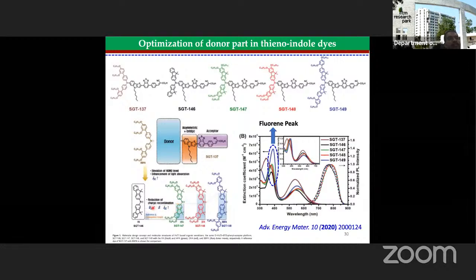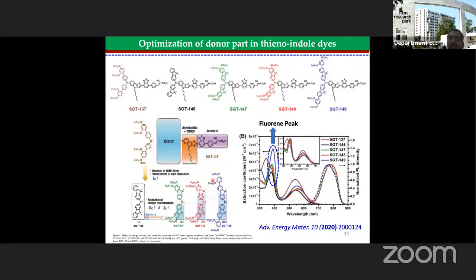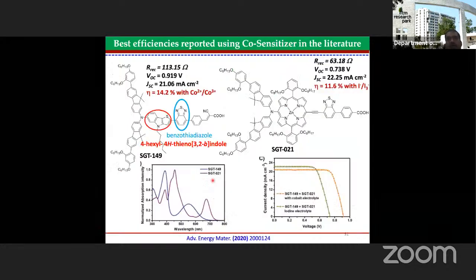So if you look carefully, the VOC, JSC goes up as you go from this green one to the red one, which has got a longer alkoxy chain, from there to the phenyl alkoxy modified fluorene. So there is a line here which shows VOC, JSC going up, okay? So now the fluorene substitution on the triphenylamine seems to be an interesting way to reduce the recombination, that means over potential, later the recombination will go down.